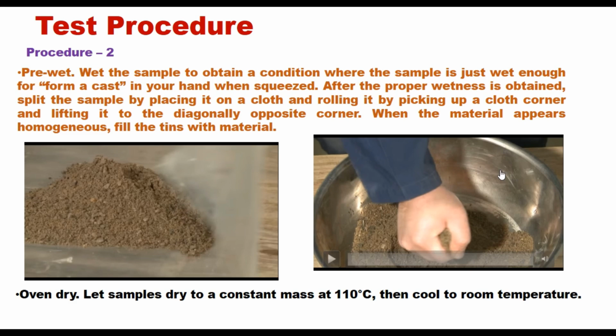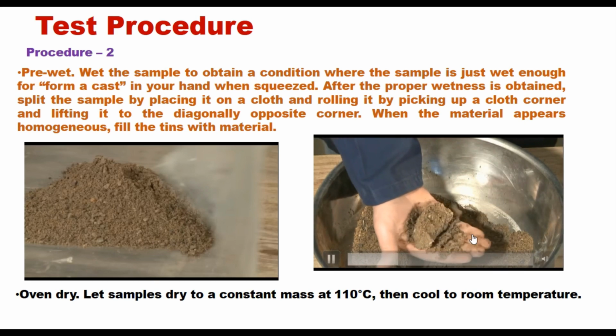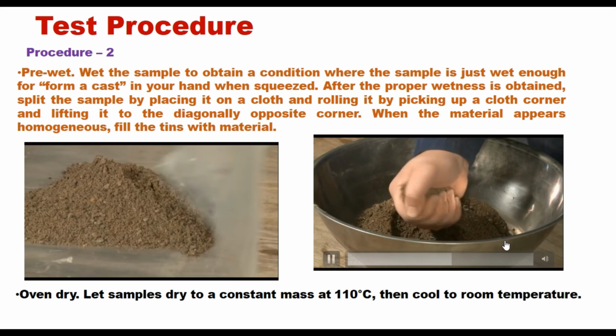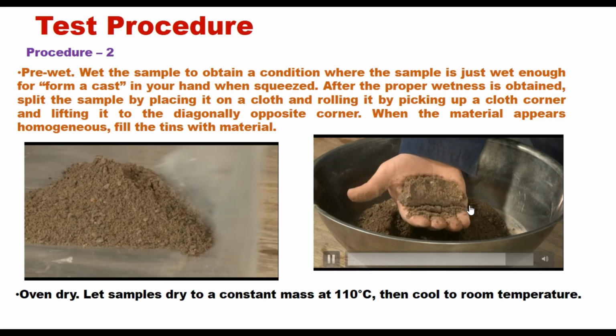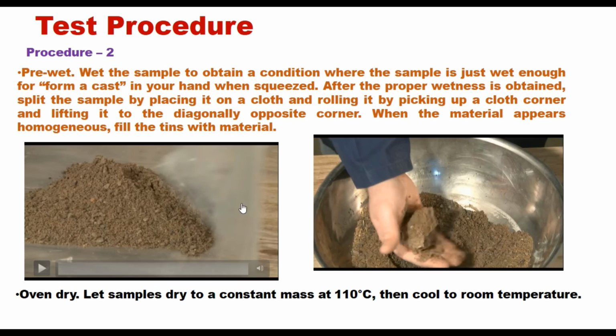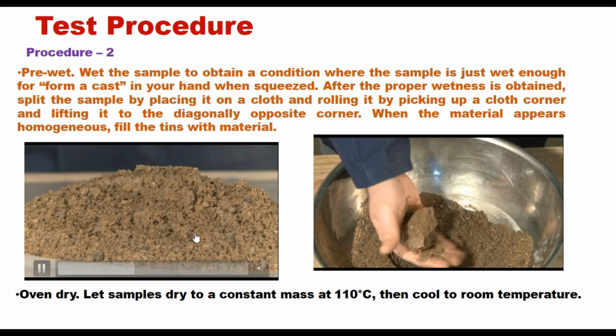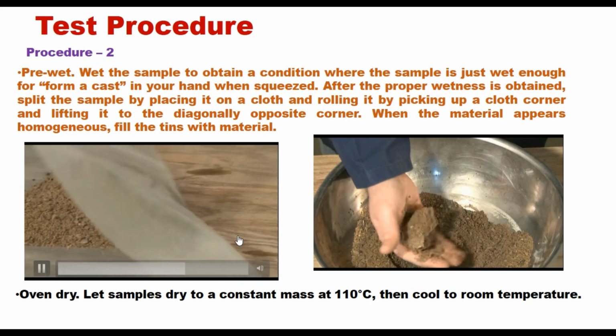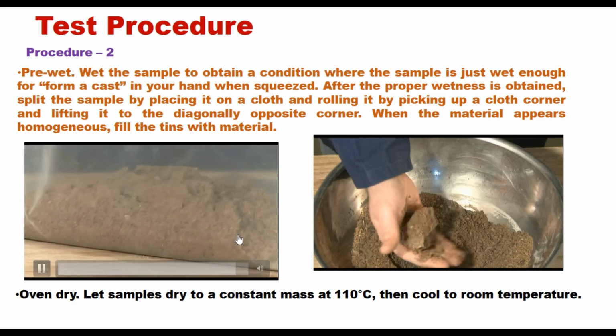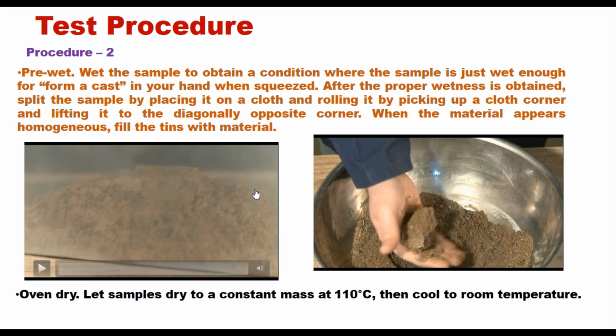The second procedure is that we pre-wet the specimen. Wet the sample by adding water to obtain a condition where the sample is just wet enough to form a cast in your hand when squeezed like this. After proper wetness is obtained, split the sample by placing it on a cloth or on a plastic sheet and rolling it by picking up the corner of the sheet and lifting it to the diagonally opposite corner. When the material appears homogeneous, fill the tins with the material.